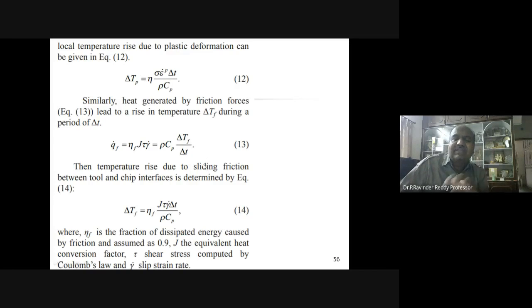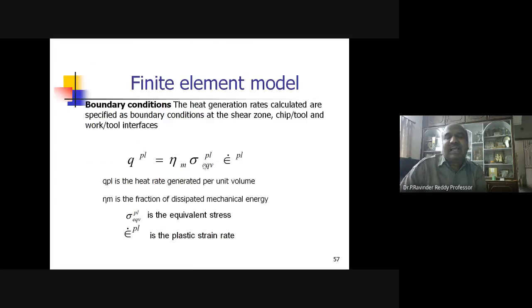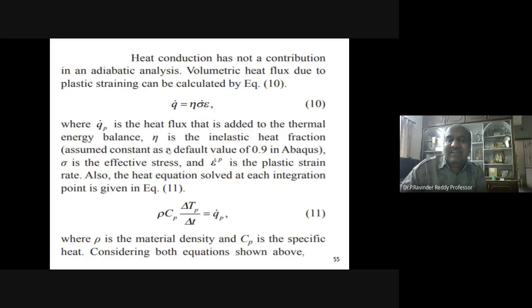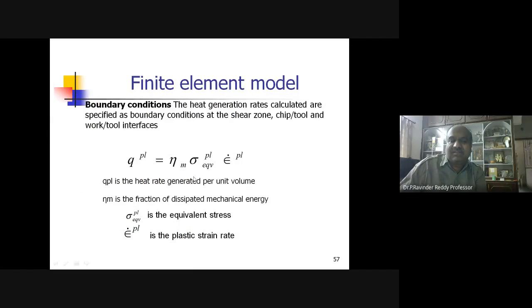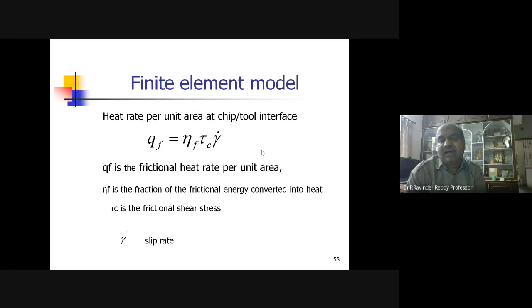When you again link this thermal variation in transient condition to the damage mechanics, thermal and fracture we have to couple, and we can calculate. Generalized boundary conditions, coupling all the flux, have been written in a generalized way. Q of plastic: you have the mechanical coefficient and stress at the plastic equivalent strain rate at the plastic rate, and heat rate per unit area at the chip-tool interface. So here fractional heat per unit area, you have a fractional coefficient, then you have a shear at that location, then you have strain slip rate.